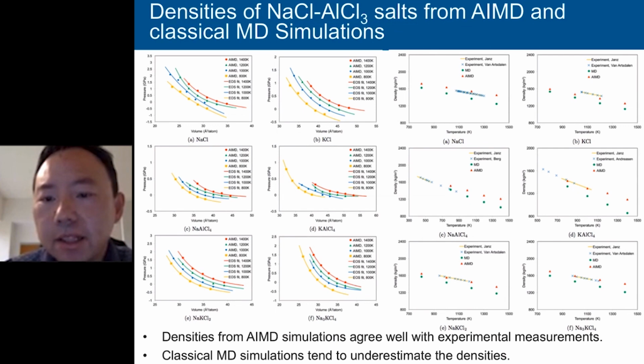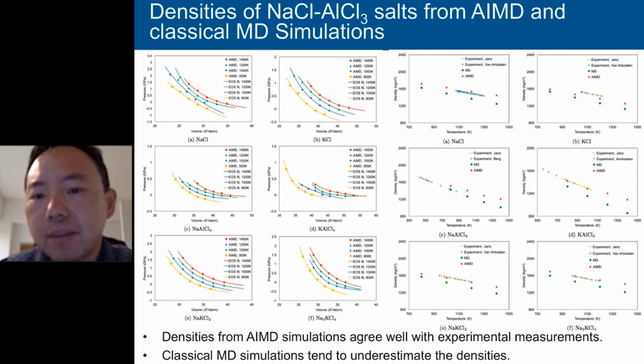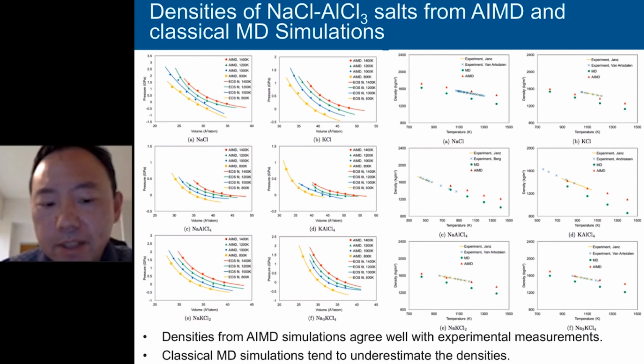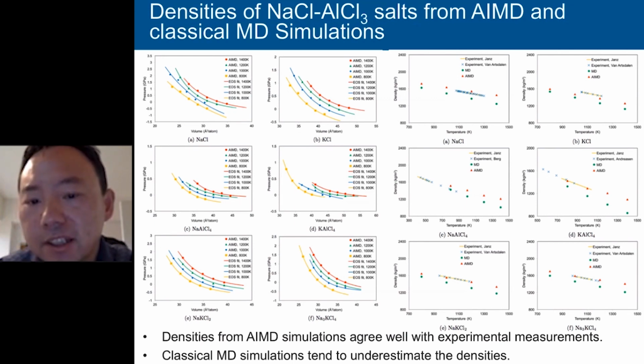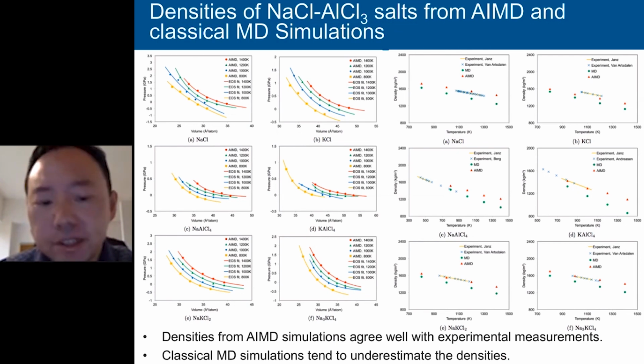So it's a very challenging task to predict even the density very accurately using the classical MD. If you look at the right figures, where I show the results from Ab Initio MD, classical MD, and experiments, you can see that the densities from Ab Initio MD always agree much better with experimental measurements. For some of the cases, the agreement is excellent. It can also be seen that although the classical MD simulations did a good job of predicting the density with reasonable accuracy, they always tend to underestimate the densities for all the systems we look at.